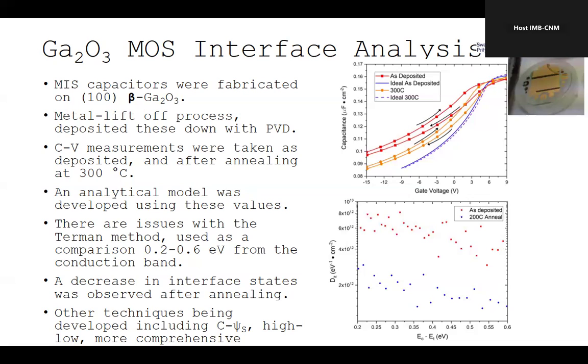The other issue for me with gallium oxide, in addition to reliability, is that the bulk mobility is only 300, I think, right? Well, being very optimistic, I think the maximum is below 200. Yes. And don't get me wrong, I'm a big advocate for gallium oxide, and it's an exciting field. But for very high voltages, 6.5 kilovolts, 10 kilovolts, that is territory not even occupied by silicon carbide at present.